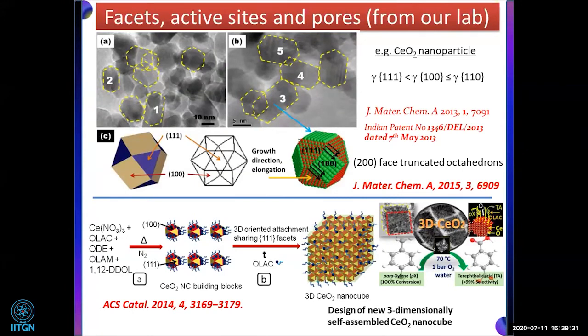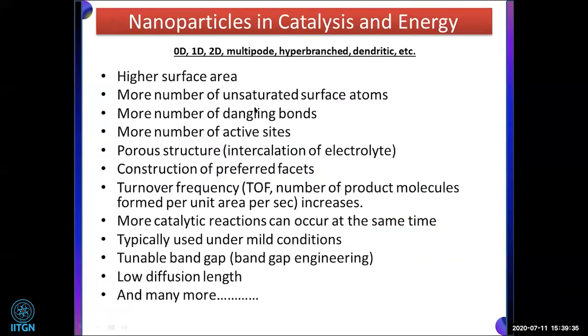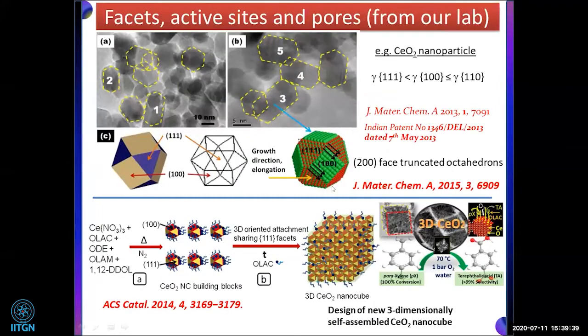So what we learned, as I said, is the more number of active sites or construction of preferred facets. This is our experience from our group. We prepared cerium oxide nanoparticles at the beginning. These particles had a truncated octahedron shape, as you can see here. And these particular shapes were exposed mainly with 100 planes. We know that gamma is the interfacial energy of the facets. This energy is very high for the 110 or 100, and very low for the 111 plane. That means the 111 plane is the most stable plane. So if a nanocrystal is exposed to the 111 facet, it will be less reactive. And if it is 110 or 100, then it will be more reactive.